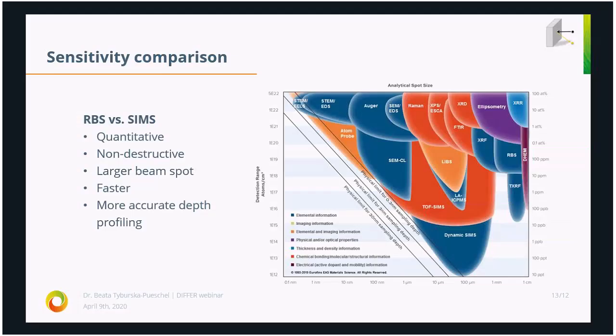This is not the case in our chamber, but could be something in the future if there is interest for it. RBS is definitely faster than SIMS. Usually you need 5 to 10 minutes per beam spot, and it's definitely more accurate in terms of depth profiling compared to SIMS.